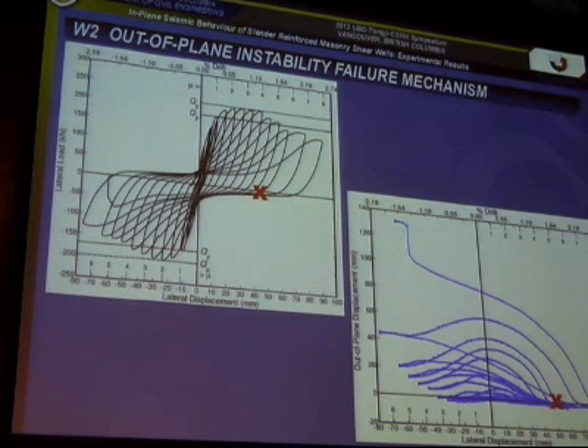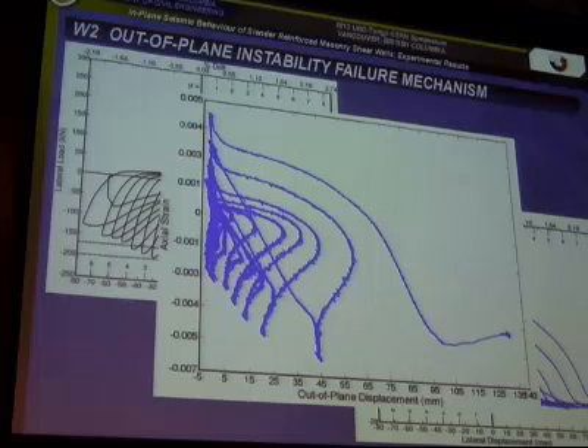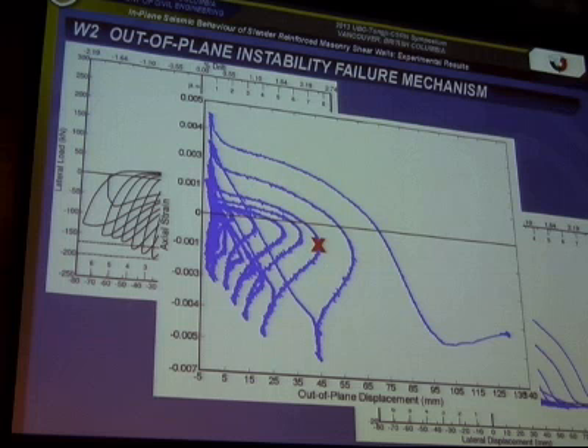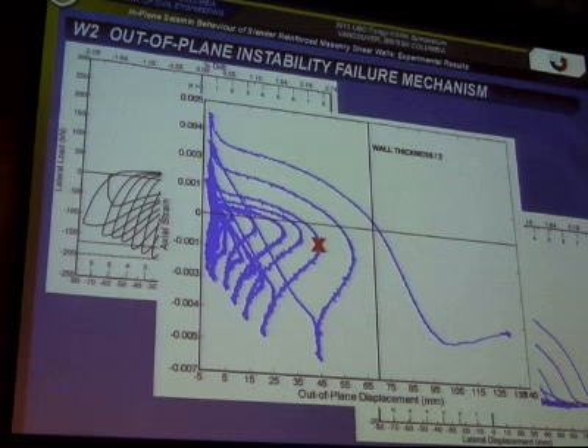So looking at the overall response, you can see that the out-of-plane displacements occur at a pretty low lateral load, which confirms the first phase's results, as well as the maximum out-of-plane displacement occurring at around 0 lateral displacement, which corresponds to a low axial strain, which also confirms the first phase's results. So as you can see, this behavior continued for a number of cycles until the critical limit of the out-of-plane displacement, half the wall thickness, was reached, upon which the out-of-plane displacements became unstable.